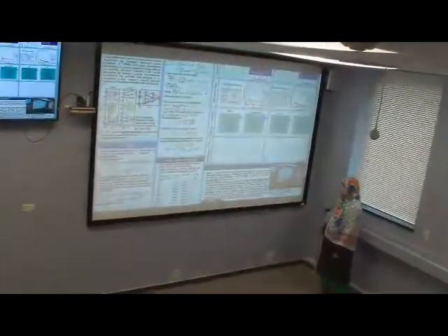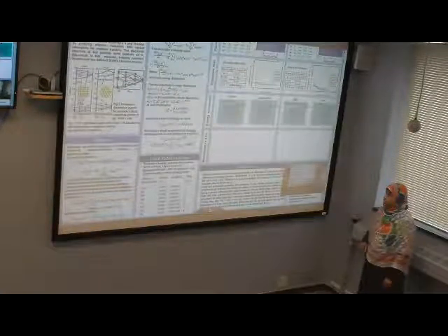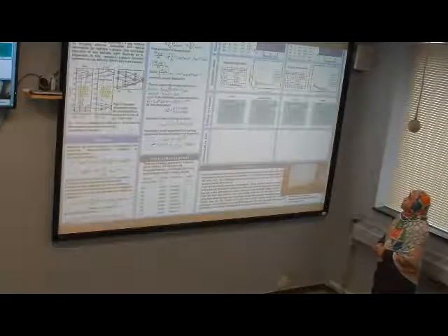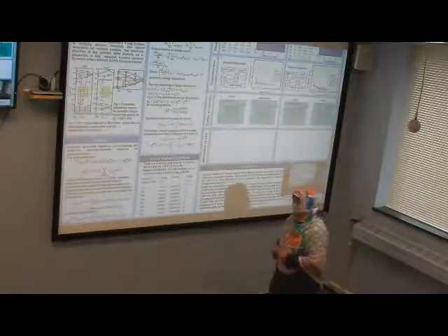Okay, here is a summary of the outcome of this research. The conclusion is indirect transition is quicker than direct transition. So indirect transition is always quicker than direct one because in indirect transition there are more pathways for relaxing. That's why. And we saw that for the first couple of states, the relaxation rate follows the gap law, and after that at higher energies it follows the inverse gap law. And I would like to request Javi. That's all.